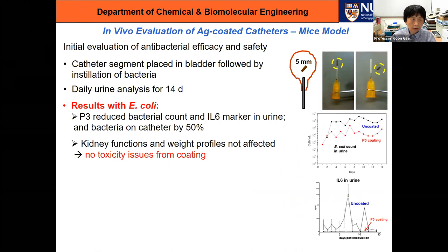So this is the result with E. coli. This is the bacterial count in urine. The uncoated catheter, you can see, has a higher bacterial burden in the urine compared to the P3. And this one is the interleukin-6 marker, which is an indication of inflammation. So you can see again that the uncoated catheter gives rise to more inflammation than the P3 coating. And we didn't detect any toxicity issues because the kidney functions were normal and the weight profiles were not affected.